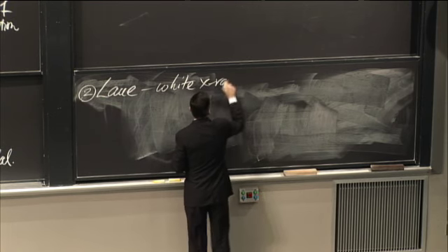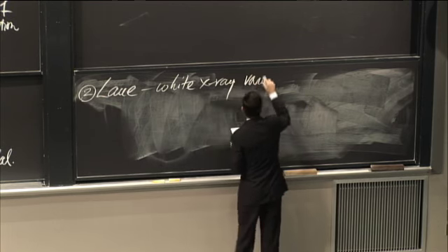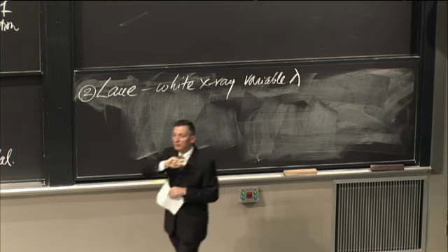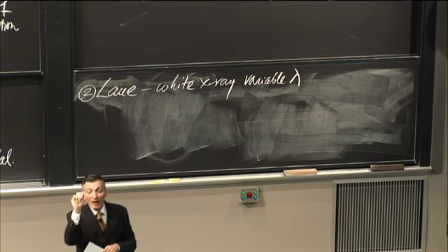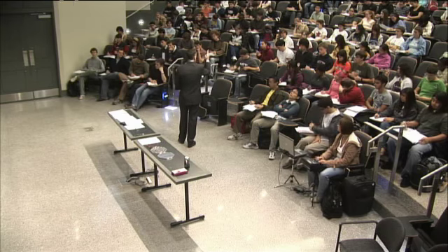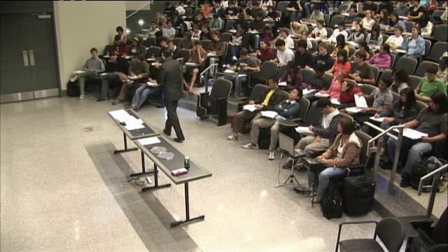White X-rays. That means variable lambda. So how would you get a fixed value of lambda? Well, you'd pick off one of those lines, like maybe the K-alpha line, because it's a nice singular line, and repress the Bremsstrahlung and so on.